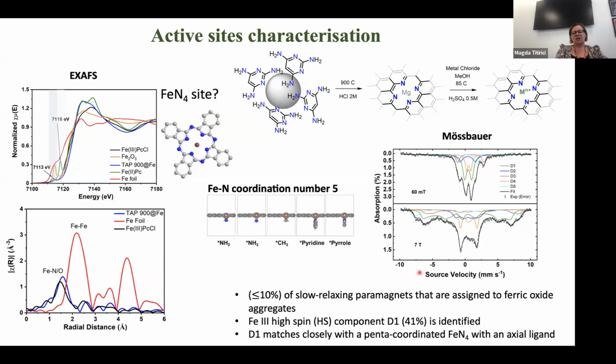Another thing when you do the single atom catalyst is how you characterize this material. This is quite key, and it's very difficult to prove that you have the single atom sites within your catalysts. So the best method is a combination of methods. One is called Mössbauer spectroscopy, and it looks at the state of iron, and it tells you which iron is high spin, which iron is low spin. It tells you about paramagnetism or ferromagnetism. And if you work with experts, I know a Mössbauer expert, you can learn a lot on how to deconvolute these Mössbauer spectra to figure out what coordination you have in your iron, and also what state of iron you have.